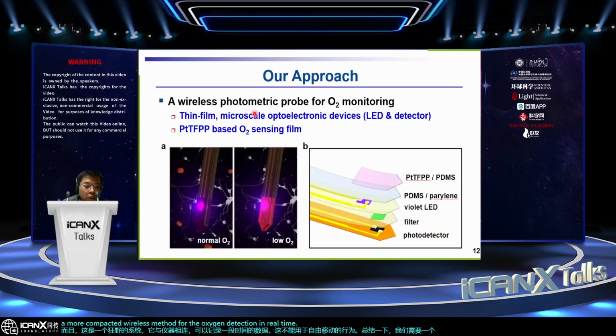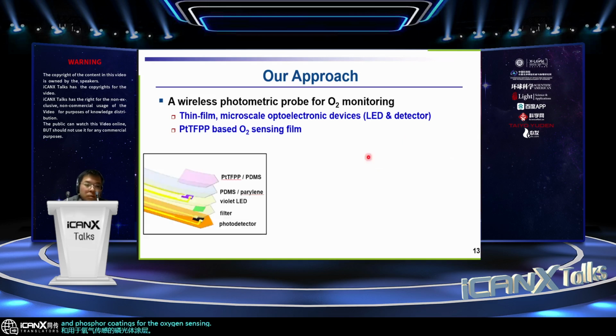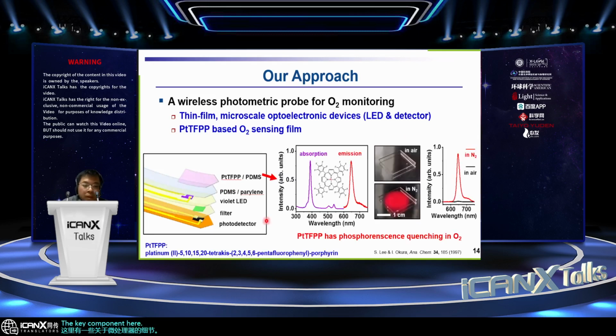And in this work, we developed a wireless photometric probe for oxygen monitoring in the deep brain. The probe integrates thin-film microscale optoelectronic devices, including an LED and detectors, and phosphor coatings for oxygen sensing. And here are some more details about the microprobe system. The key component here is the oxygen sensing film based on PtTFPP in PDMS.